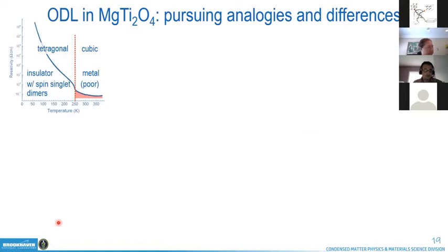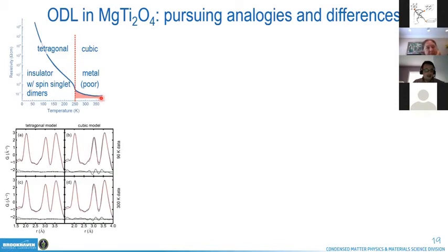We're going to move on to the titanium variant, which again, if you take a look at the resistivity, has a quite poor metallic state. As it turns out, at low temperature the system has a tetragonal average structure, and at high temperature it's cubic. If you fit the tetragonal model to the low temperature data below the transition, you get a much better fit than with the wrong cubic model. You can see in the PDF over the first few peaks how the cubic model misfits the low temperature dimerized data.